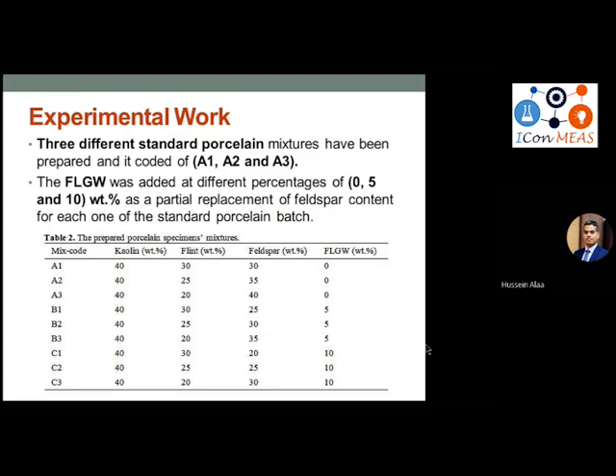Three standard porcelain mixtures have been prepared, coded as A1, A2, A3, as shown in this table. The kaolin percentage was fixed for all mixed batches, while flint and feldspar were varied. The first group, A, was composed without FLGW. Then the FLGW was added at different percentages, 5 and 10 weight% as a partial replacement of feldspar content: 5 in group B, and 10 weight percent in group C. This percent was reduced from the feldspar content.